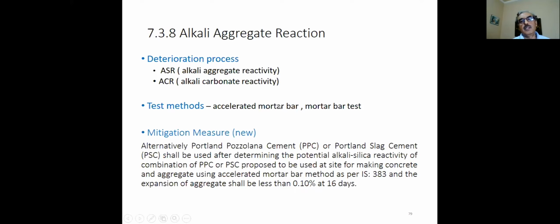Test methods: accelerated mortar bar test was not there earlier. Now we are introducing this also, accelerated mortar bar test. Mostly ASTM mortar bar test is used, so a similar test. Now we are also incorporating that, and the mortar bar test is already there, so that will follow.